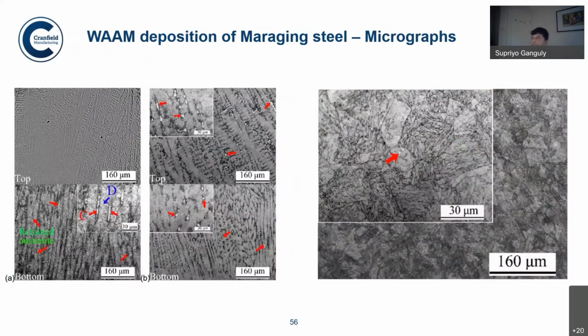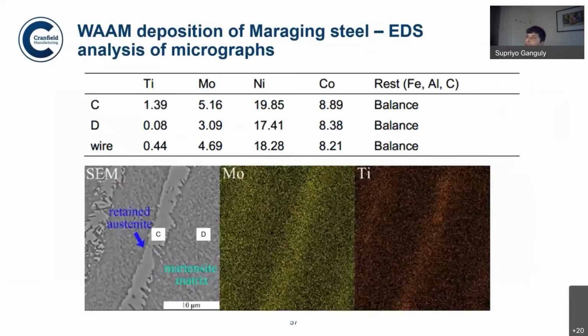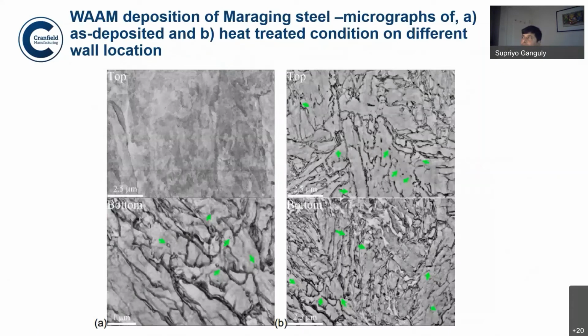This is some of the microstructural studies that were carried out to show the proportion of retained austenite at different levels of the deposit, shown here in this micrograph, and also the associated segregation. You can see here the molybdenum and titanium segregated. Some atom probe work was done to understand why the aging response is not as good as, say, with aluminium, because these are quite heavy atoms and their diffusion is not quite straightforward.